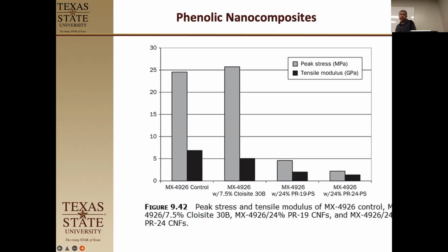Okay, so let's look at our control here. They did tensile data on these materials, and this is the control right here, where it is peak stress and tensile modulus. Adding the clay, we would expect it to have increased stress. That's the clay units of it. It didn't help the modulus that much, but it did help with the stress. And the other two materials with the two different other loadings, these are both carbon nanofibers, actually tanked those properties. So there's just too much carbon fiber there, not enough matrix.